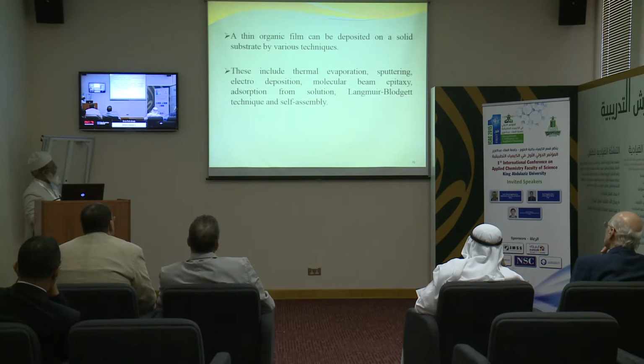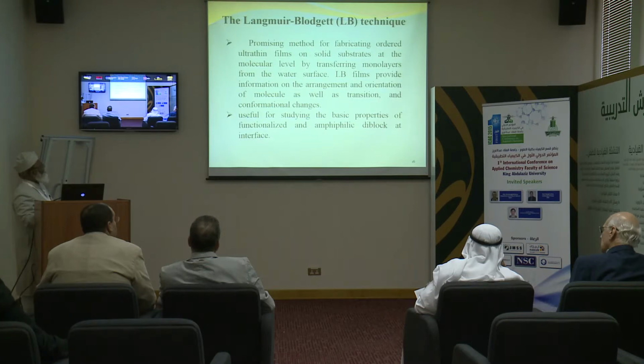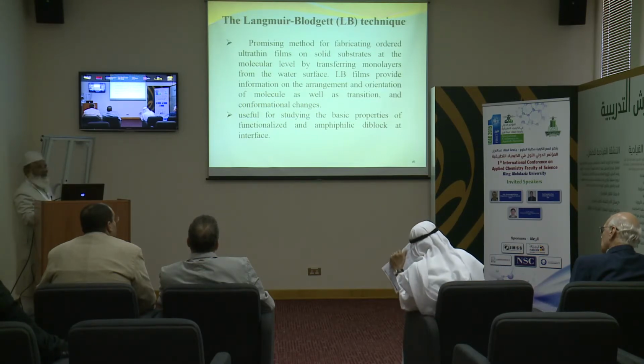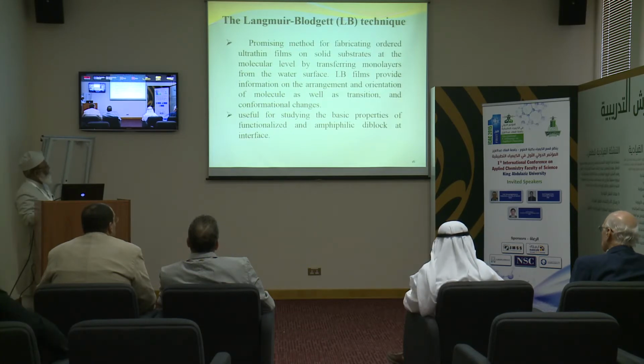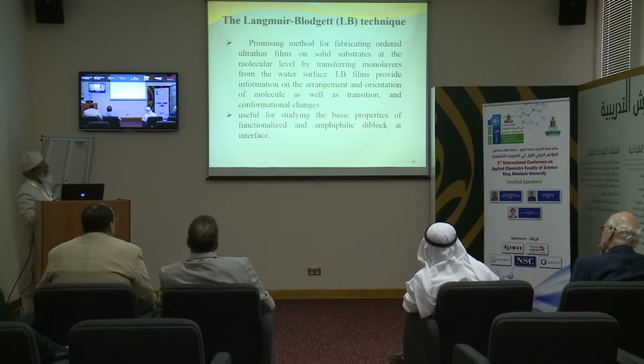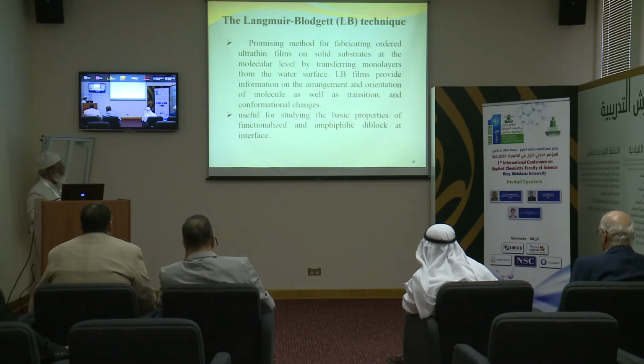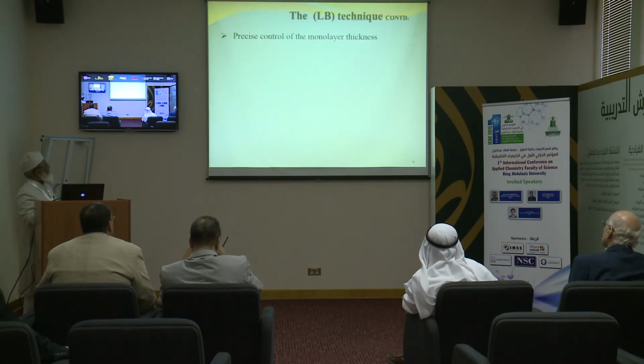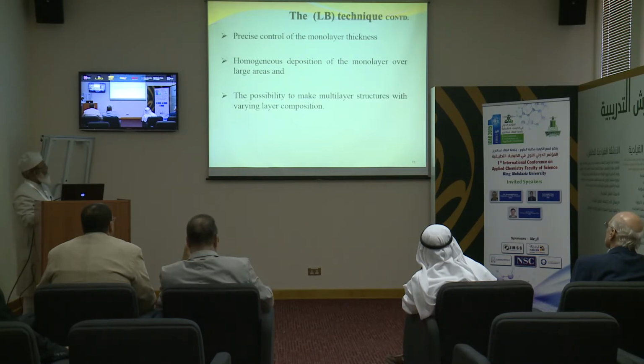So a thin organic film can be deposited on a solid substrate by various techniques. These include thermal evaporation, sputtering, electrodeposition, molecular beam epitaxy, adsorption from solution, the Langmuir-Blodgett technique, and self-assembly. The Langmuir-Blodgett technique is the promising method for fabricating ordered ultrathin films on solid substrates at the molecular level by transferring monolayers from the water surface. These LB films provide information on the arrangement and orientation of molecules as well as transitions and conformational changes. These are useful for studying the basic properties of functionalized and amphiphilic diblocks at the interface. Precise control of monolayer thickness can be accomplished. Homogeneous deposition of the monolayer over large areas can be ensured, and also the possibility to make multilayer structures with